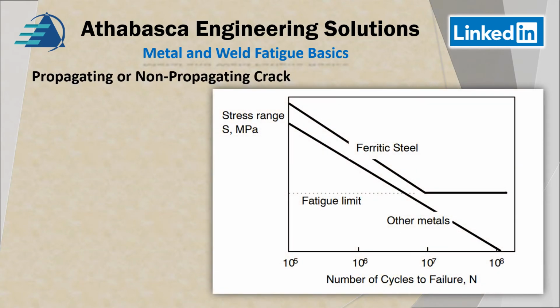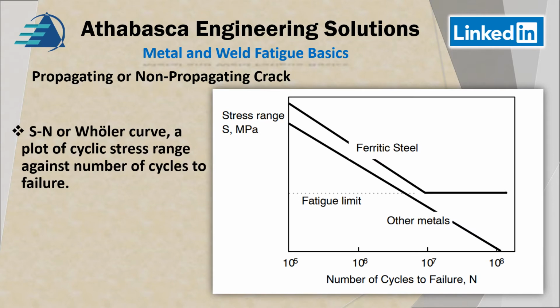Look at a curve. It's called the stress S-N curve, or the Wöhler curve, and it's a very interesting way to look at materials and how they behave in fatigue. And there's tons of data out there for different alloys and materials, looking at their fatigue properties. What's very interesting about that is this fatigue limit that you see right here. And looking at the fact that ferritic steels have a fatigue limit where the cracks don't propagate. And so if your stresses are below the fatigue limit, then your part can continue on forever.